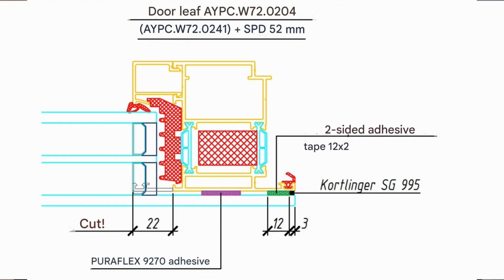of the glass. And when we glued in the glass, it turned out that you could never stick it perfectly. And somewhere it would either stick out from the glass or, on the contrary, sink in. So from the end, the edge didn't look very nice. I moved away from that, and now I asked the production team, we made drawings, developed everything, for them to stick this strip of double-sided tape about 3mm deeper so that the entire edge is taped. Then, inside, between this strip, they specifically apply this glue.